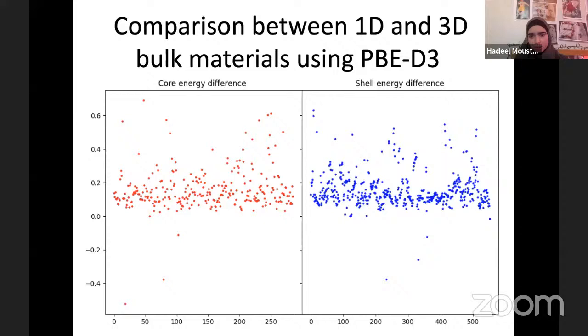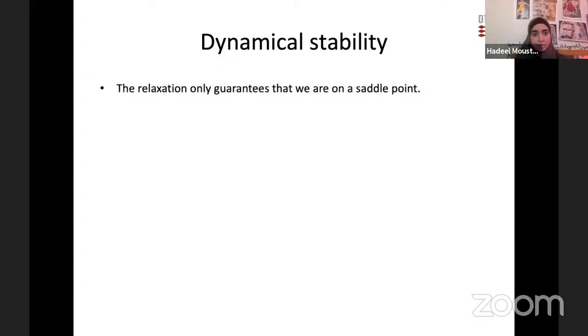Which shows that we have been lucky with our choices, as almost all of them are good enough to be done. So for the dynamical stability, the first thing we do when we look at the material is the relaxation. We calculate the relaxation, but as the relaxation only shows that we are on a saddle point, we calculated the dynamical stability, which is the phonons in the cell.